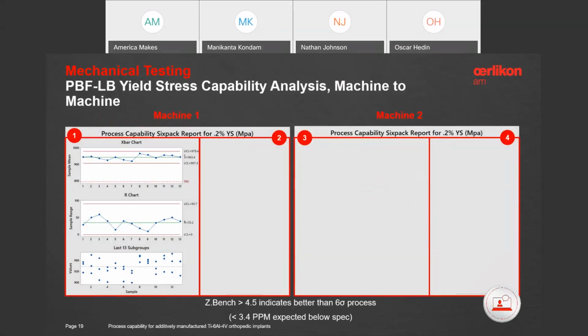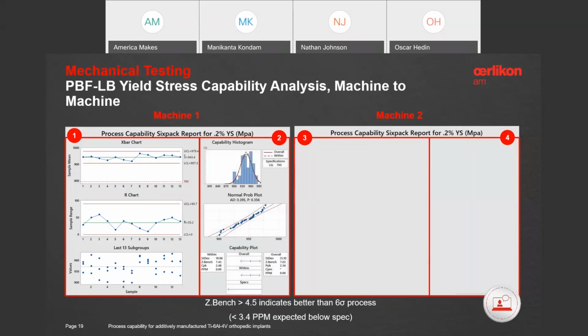Thank you, Oscar. Similarly, we did the process capability analysis for the laser machines as well. For the first laser, we plotted the X bar R charts to make sure our process was under control. Based on the X bar R charts, there were no flags raised in the process, from which we can determine that our process is under control. We also analyzed the R bar charts to make sure there was no wide spread of data or any unusual causes of variation. After checking the first two boxes, we went ahead and calculated the normality of the data. When we look at the normality of the data, the p-value was always greater than 0.05, which indicates that our data is normal, which is another indication that we can start our process capability analysis.